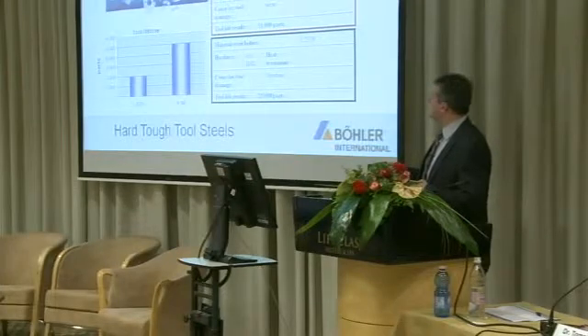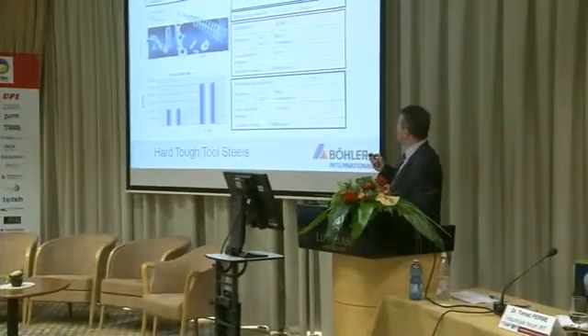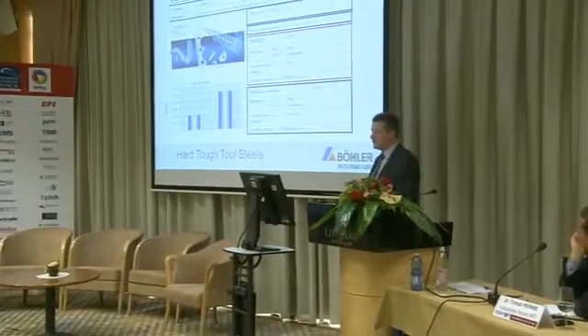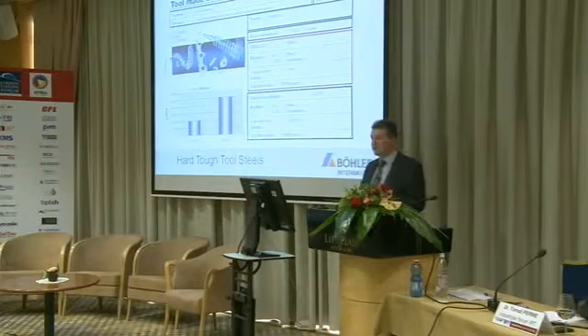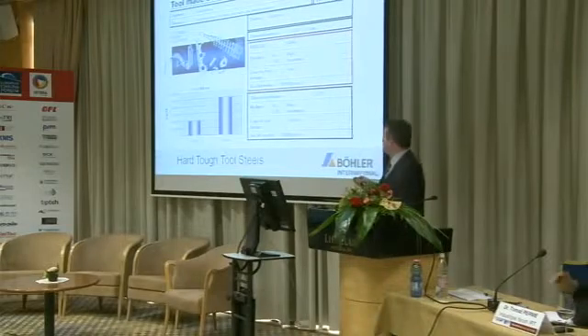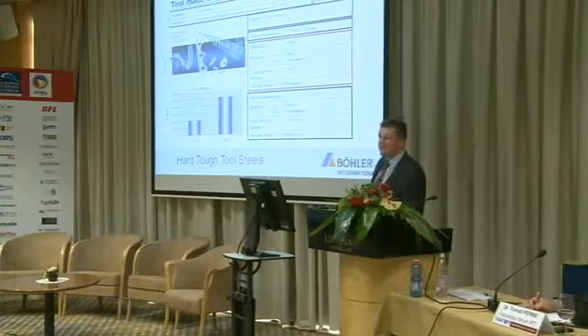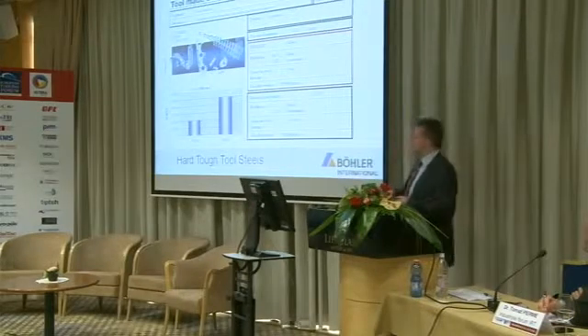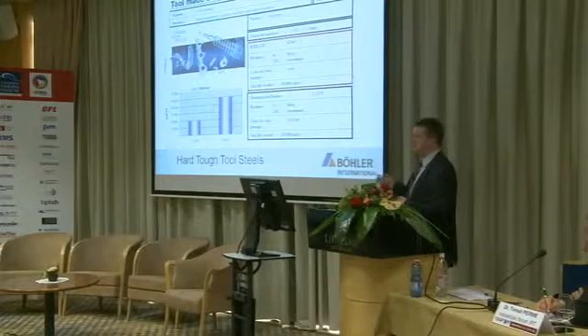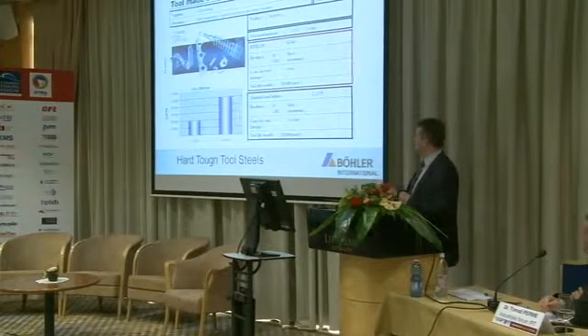And the last example of this K340 is coming from the inox industry, also very thin material, 2 millimeters. Inox material has to be processed for different applications, like you can see here, for the automotive industry or electronic industry. And the result was again the same. By using the 2379, we had, after 20,000 parts, already a fracture because of adhesive wear and toughness problems. By changing to the 8% chrome steel K340, again the right balance of the properties, we could increase from 20,000 to 50,000 parts.